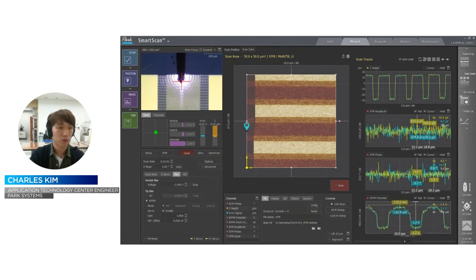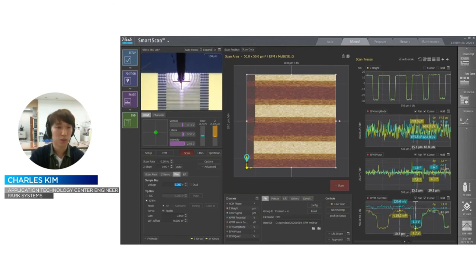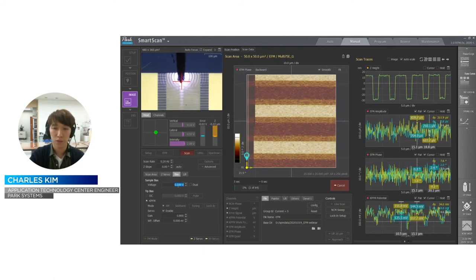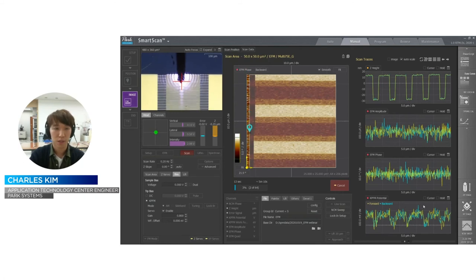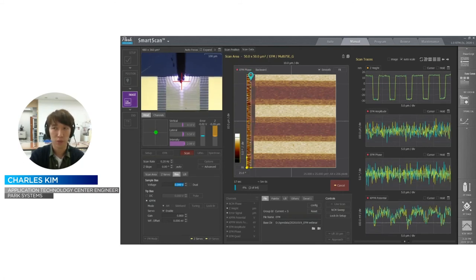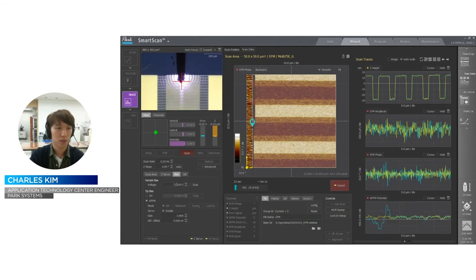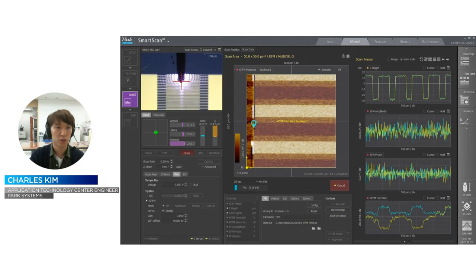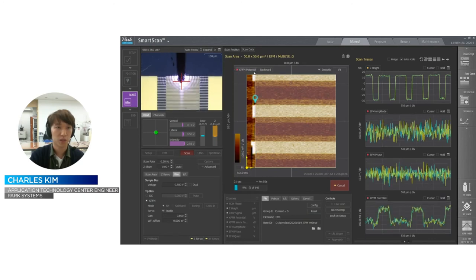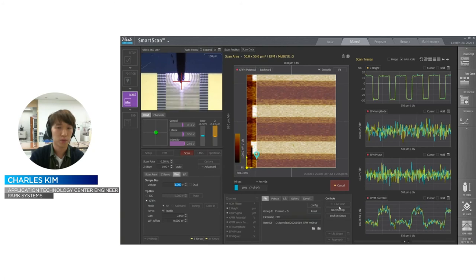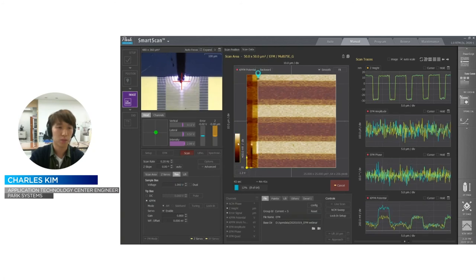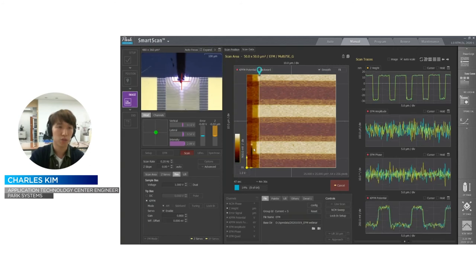So let me scan the same images. Let me start from 0 volt. Then there's no specific difference in the KPFM potential image. But if I change the sample bias to 0.5, then the potential value will change to a brighter color, like this. And if I make it double, then it has a brighter color than the 0.5.